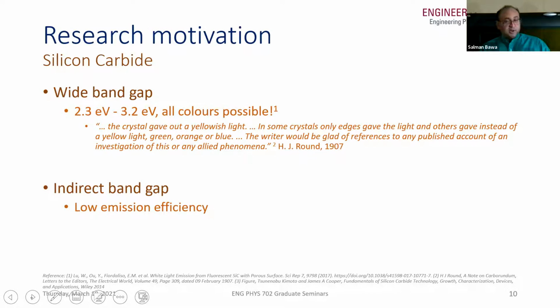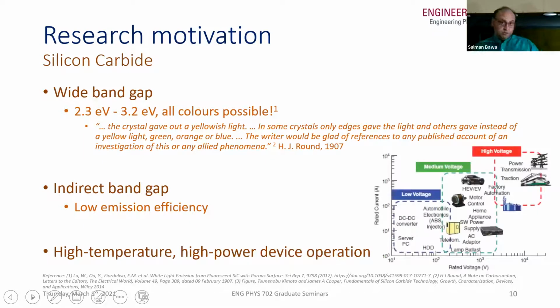Now, the challenge here is that silicon carbide has an indirect band gap, which means just like silicon, the recombination mechanism would be phonon assisted, and therefore the efficiency would be lower. However, silicon carbide has been used vastly in the electronic industry. And you can see from the graph on the screen that silicon carbide has been used for high temperature, high power device operations because it can withstand the high temperature, high power requirements.